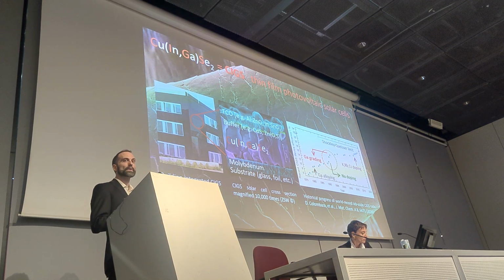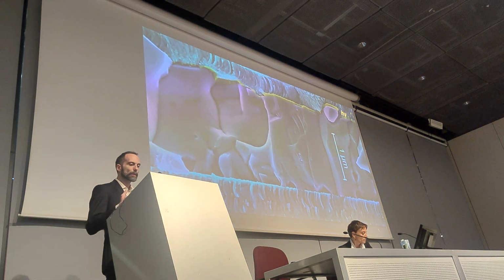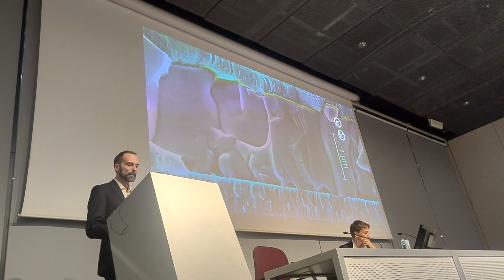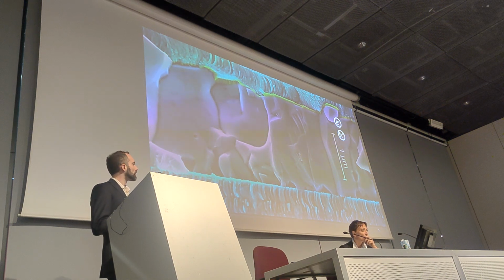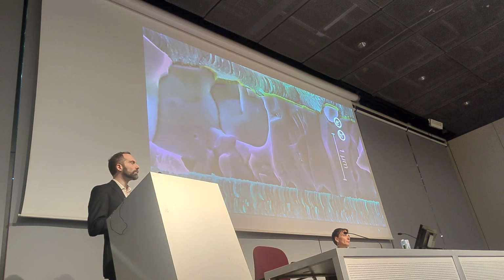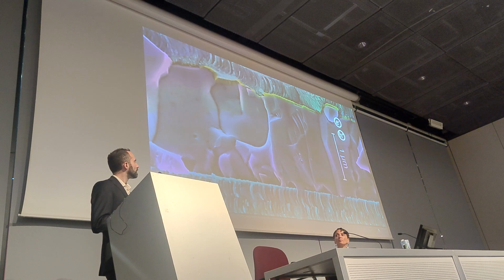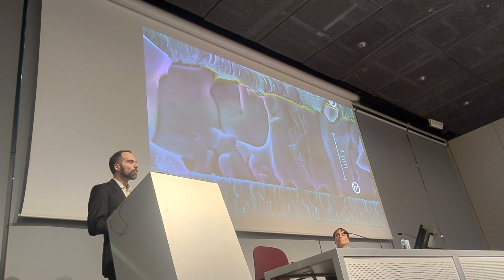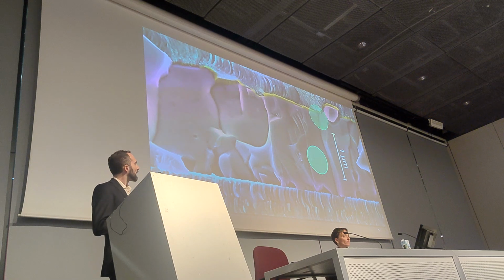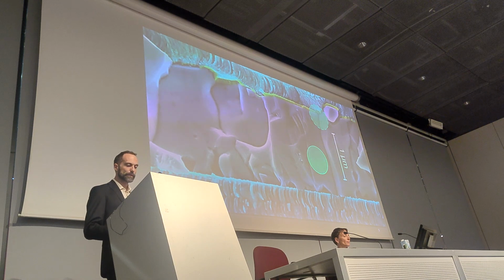That is just 10% absolute away from the maximum Shockley-Queisser limit that's achievable with a single junction solar cell. So whenever we have absorption of a photon of a suitable energy in the CIGS, we have generation of an electron-hole pair. And whenever we have electron-hole pairs, there is a high chance for them to recombine. And if we look at the microstructure, it's a real wonder that this material works at all. You look at this, we have small grains, we have high surface to volume ratio, high density of extended defects, grain boundaries, and surfaces. So one of the main reasons it worked at all is thanks to the sodium itself, and we look into why this is the case.